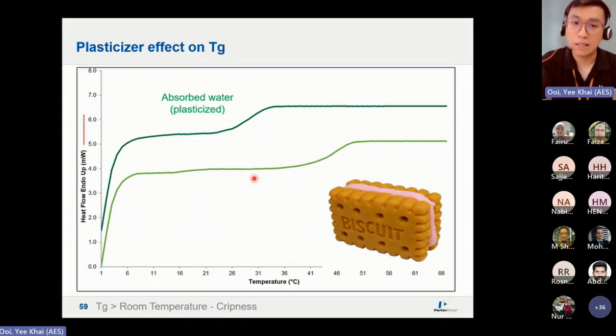That means before the transition, it is like glass at room temperature. For example, it's brittle, it's glassy. So in biscuit terms, at this stage it's glassy, it's crunchy, it's brittle, but once it passes through the TG, it becomes rubbery, it becomes soggy. Now, without absorbing water or moisture from the surroundings, your TG is at 46, for example, or 40 something. So if I store my material at room temperature, for example at 21 or 26, it's still in the glassy state. So your biscuit is still very much crunchy.